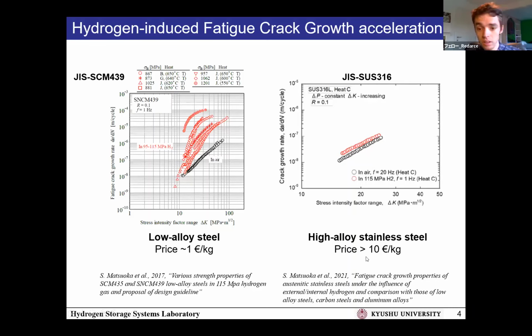Here I show an idea of prices: it can be over 10 euros per kilo for this stainless steel. In my thesis, we're focusing on cheaper materials that would be, for now, at the raw price around 1 euro per kilo, for example. The main problem is that with the fatigue crack growth, again in black when it's tested in air, and in red when it's in hydrogen environment, we can see that the behavior is not good at all in hydrogen environment.